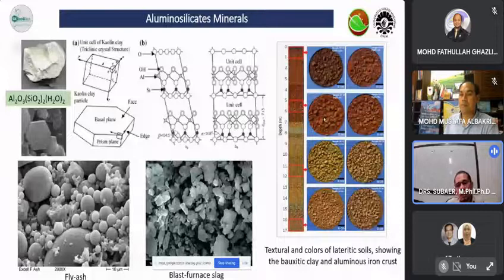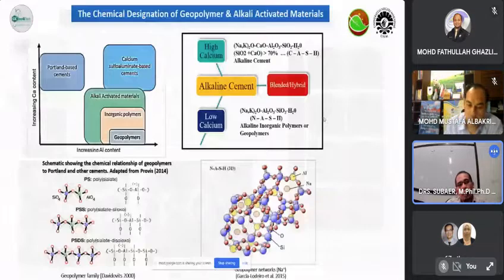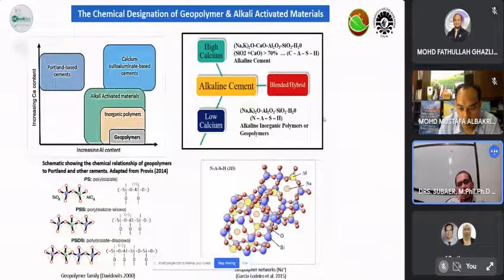And blast furnace slag, as you can see, the morphology is not uniform, like chunks of material. Very different from the morphology of fly ash. The geopolymer world is actually a part of inorganic polymers. You can see the position of geopolymer as a cementitious material. It's a part of the alkali activated materials. So geopolymer is actually a very special topic within alkali activated materials.